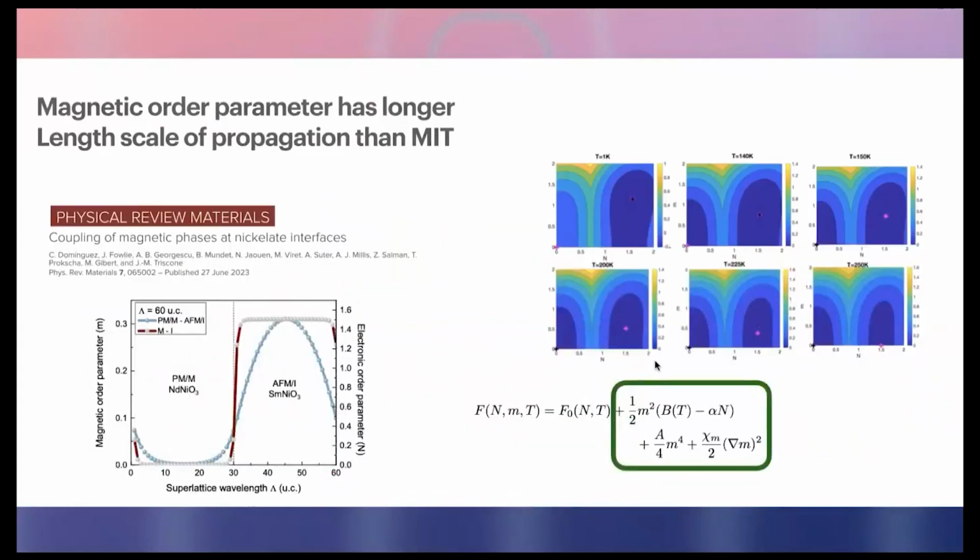And I should mention this is an ongoing collaboration. We had quite a few more papers since. In this one, for example, we also studied the magnetism. And one of the interesting things is, the antiferromagnetic order in these materials in the bulk material only exists in the insulating state.